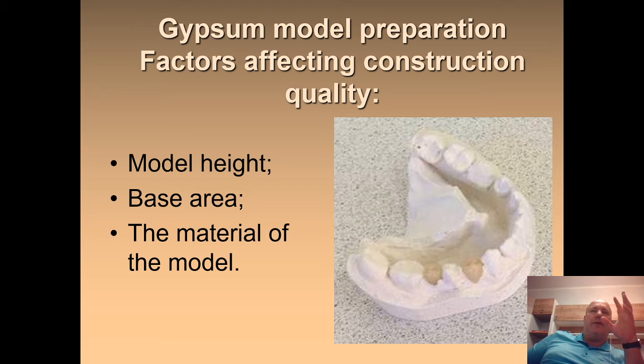And the third part is the material of the model. Models can be made of a variety of materials: stone, gypsum, even acrylic. With each of these materials, the density of the model changes. The higher the density, the harder it becomes to create pressure for the model using vacuum type machines. There are three solutions to this problem. Use vacuum pressure based molders, but they are usually more expensive. Drill a hole to use a fenestrated model in the area of the palate or tongue to facilitate suction in these vacuum pockets. Use gypsum models. This is the third variant. Gypsum is a porous material, and the vacuum molder will be able to create a vacuum right for the model.